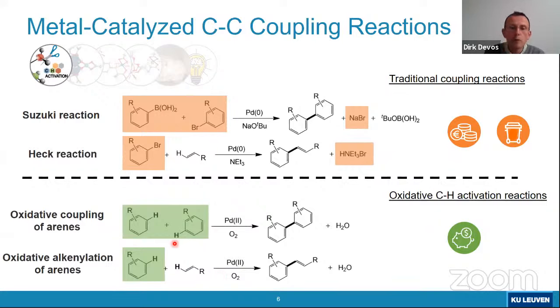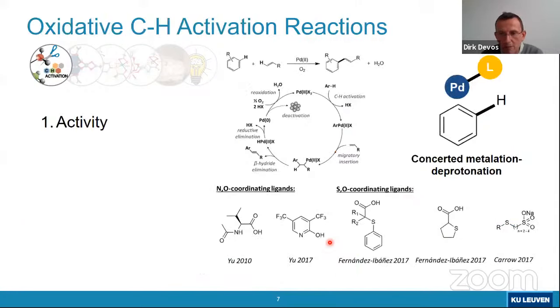So at least from the viewpoint of the precursors, this is attractive because you start from cheap molecules in this case. And also the advantage, of course, is that, for instance, if you do it with oxygen, then your waste product, your byproduct, is just water. Even if you would use an oxidant like TBHP, your byproduct will just be tertiary-butanol, which is still quite acceptable in comparison with, let's say, inorganic halogenated waste.